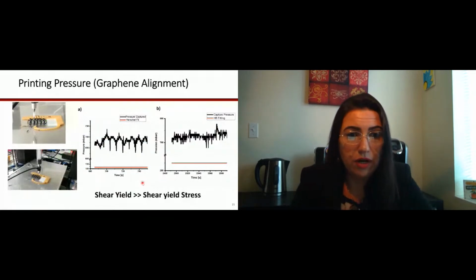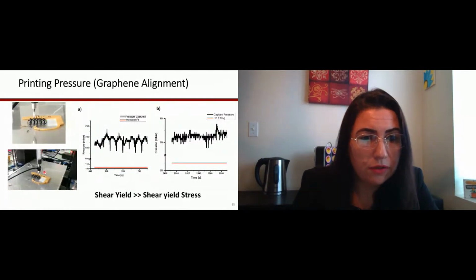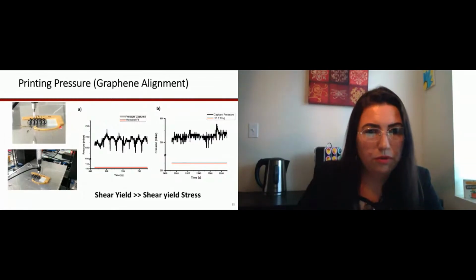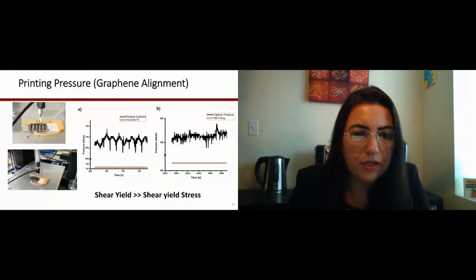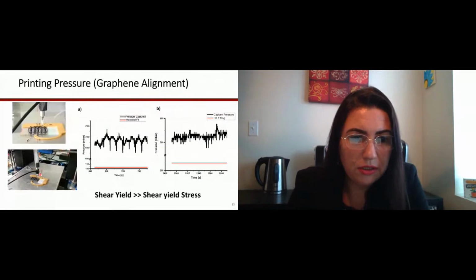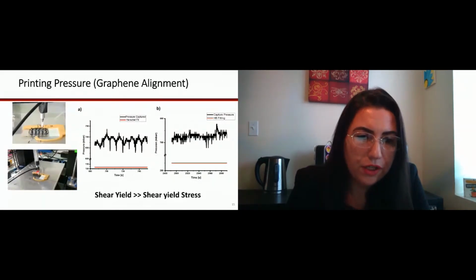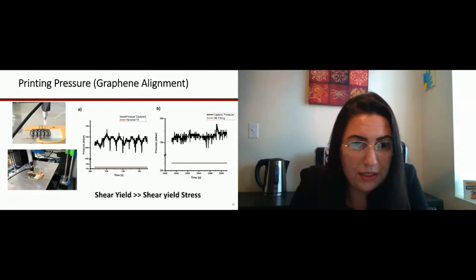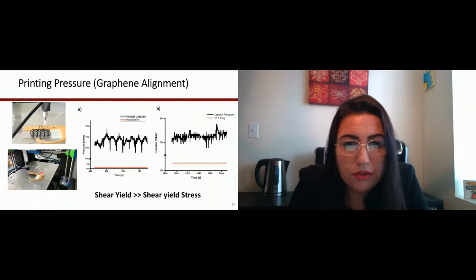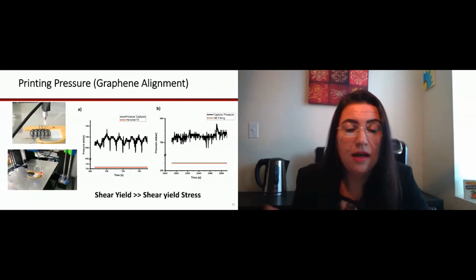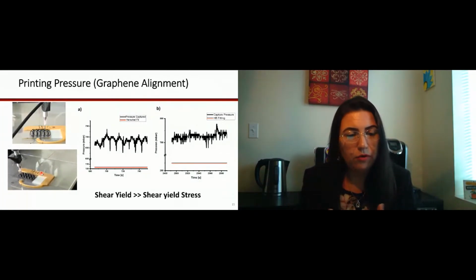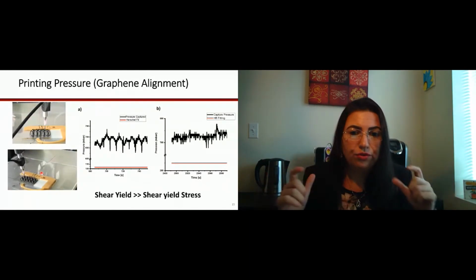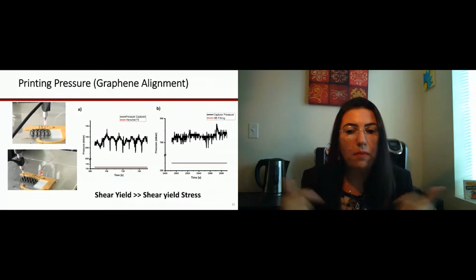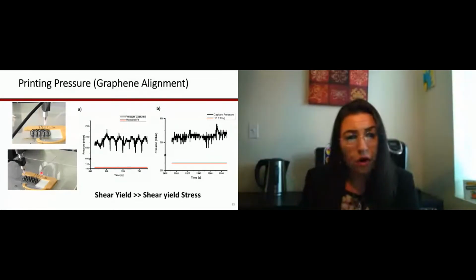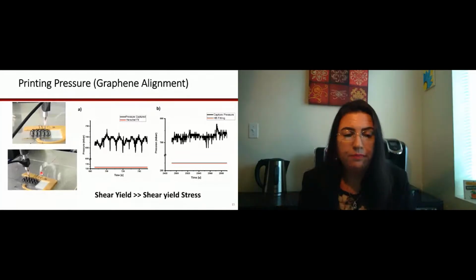shear yield stress. The video, if it shows, I'm not sure if it's showing. Okay, so as you can see here on the video, there is a black part on the 3D printer, and the black part over here is just what measures the pressure as you're printing. And this pressure was really important to prove that we're actually having the alignment. So in chemical engineering, when we learn about flow and plug flow, we make sure that this shear yield is exceeded. So we did that for all our samples, and we were able to 3D print all the different samples.